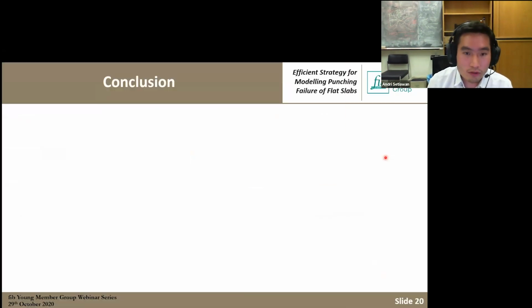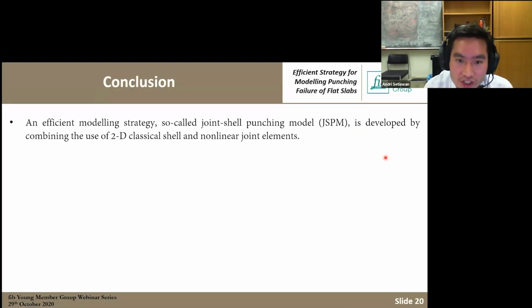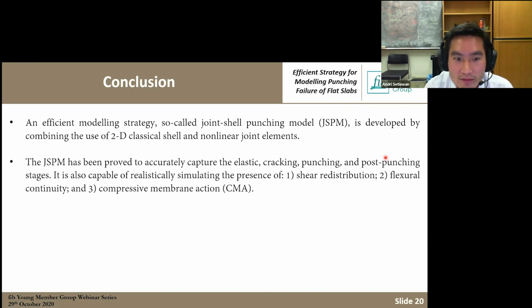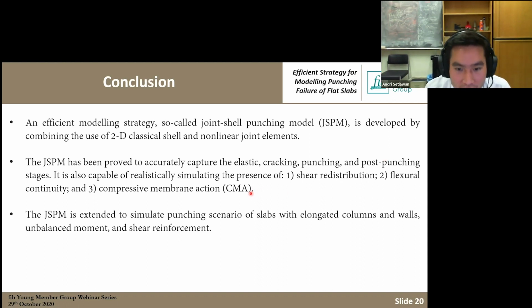So to conclude, we are developing an efficient modeling strategy. We call it the joint shell punching model, the main idea of which is combining the use of 2D shell and also nonlinear joint elements. And we have sufficiently proved that JSPM captures the elastic, cracking, punching, and post-punching stages reasonably well. And we can also take into account the shear distribution, flexural continuity, and CMA. And we have also extended the model so that it can handle the punching of slabs with elongated columns and walls, slabs with unbalanced moment, monotonic and cyclic, and slabs with shear reinforcement. So we have, let's say, covered many practical design scenarios.